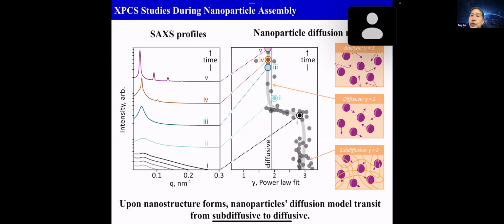And then this is where we get into how you're going to organize the system, because you do need the driving force. Even if it's a colloidal particle assembly, you need the concentration to provide that entropic driving force for them to arrange. This is where we get to XPCS. So we did in situ XPCS to look at the diffusion mode of the particles and use that to infer the surrounding organic matrix organization, as well as to see the system diffusivity or mobility across different length scales. The left is the small angle X-ray scattering profile that helps us identify the window where we should do the XPCS analysis.